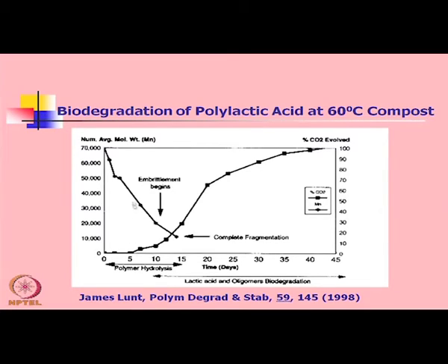You see the molecular weight has come down from 70,000 average molecular weight to almost 10,000 molecular weight fragments. And it shows almost complete biodegradation, 100% biodegradation, in 40 to 45 days time period.